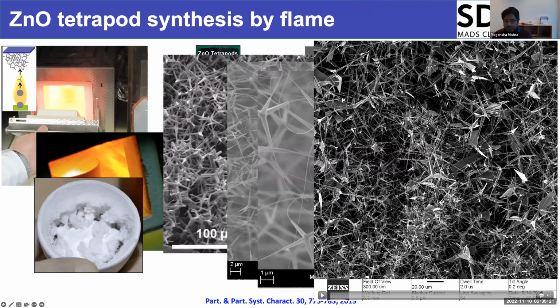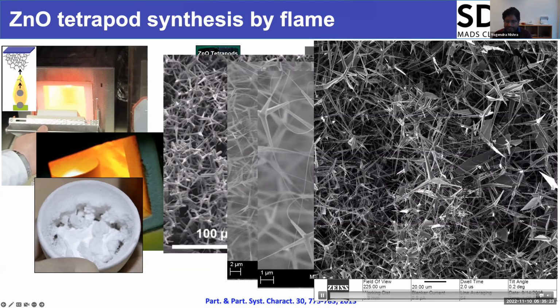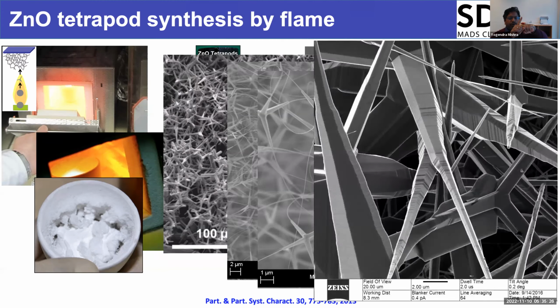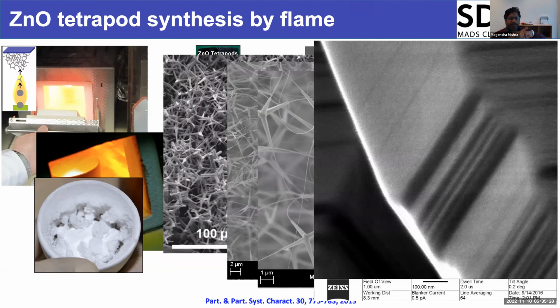Well, why micro and nano? The simple answer is that when you imagine one arm, probably you imagine that this arm is smooth from bottom to top, but that is not the case. It has a lot of staircase structure, which adds much more surface to the nanomaterial. And this surface is accessible in a very nice way because of the three-dimensional self-assembly. So that makes these tetrapods very, very unique. There is no chemical involved. It's purely zinc oxide material, but this works very, very well.